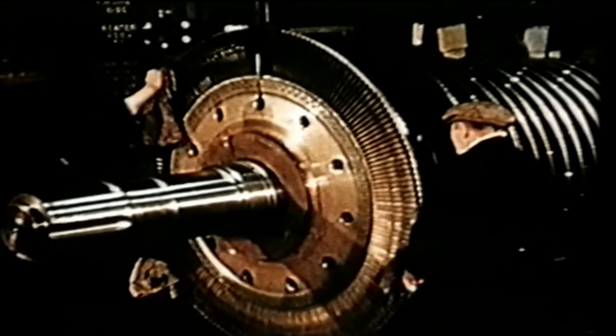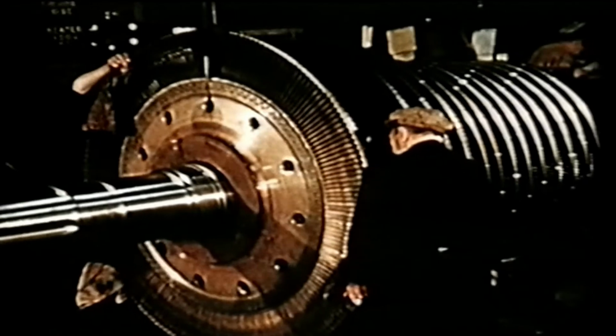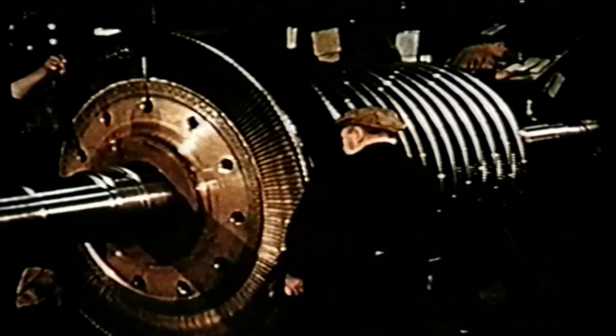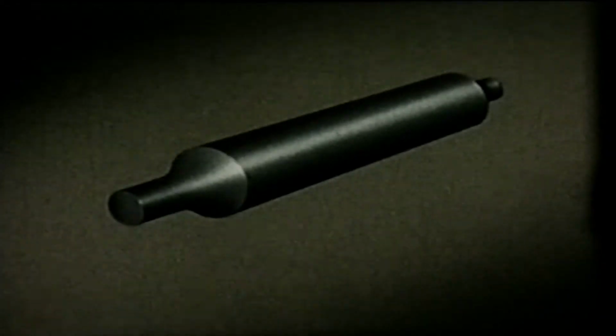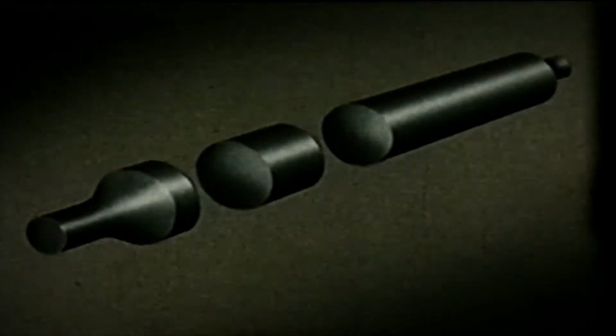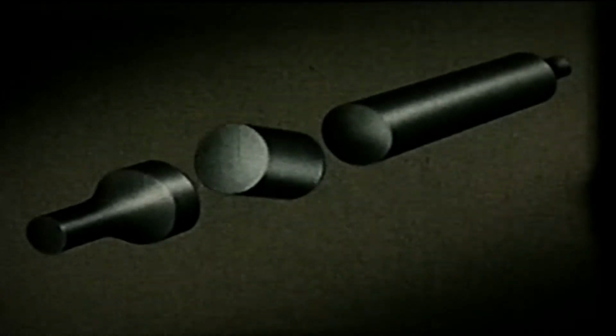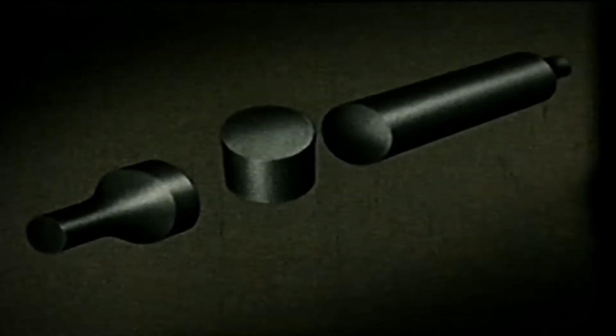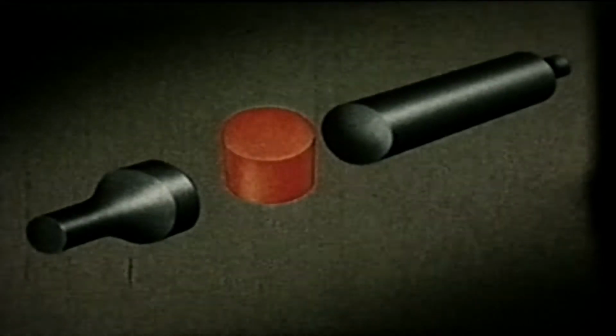Other types of turbine rotors are built up by fitting separate discs onto a central shaft. For the production of these discs, an ingot is first forged to a round bloom from which individual blocks are cut. These blocks are then forged at right angles to the original ingot axis. This upsetting operation changes the grain flow as shown by the lines in the diagram. It ensures the best properties in relation to the stresses to be encountered under service conditions.